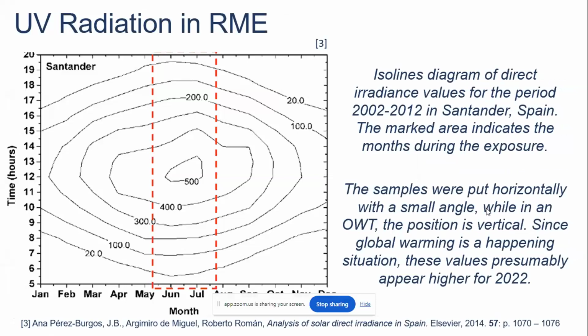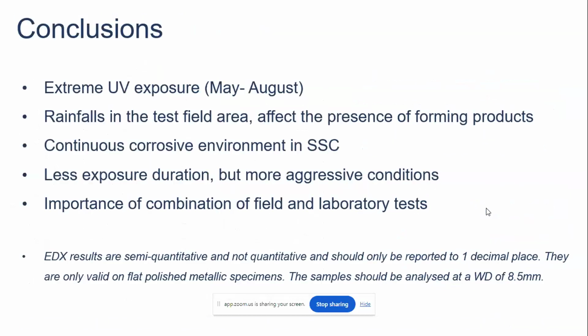In order to have a safer conclusion of why these differences happened in the real marine environment and in the salt spray chamber, we found some previously reported data that from May till July, when the exposure took place, the sun conditions are quite extreme. So this is possibly a reason why this difference was reported. To conclude, it was not only the extreme UV exposure, it was also the rainfalls in the test field area, which also affected the presence of forming products.